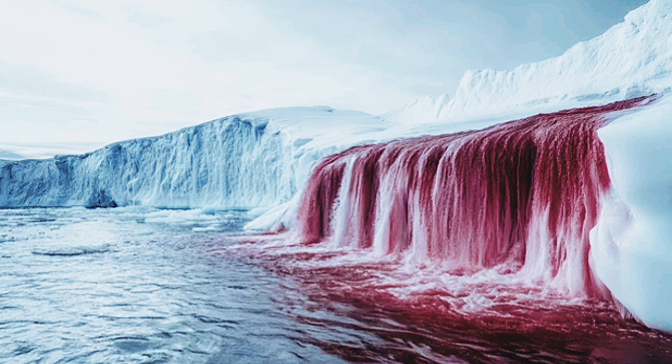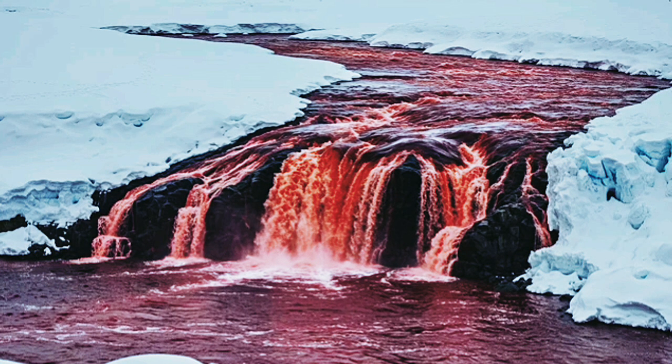Well, this is where it gets really interesting. They used XRD, which is sort of the standard for identifying crystalline minerals. Everyone expected to see strong signals for things like goethite. But the XRD results were underwhelming on that front. They found surprisingly little evidence for well-crystallized iron oxide or hydroxide phases. The expected signatures just weren't really there in abundance. Hold on. So the main suspect, crystalline iron oxide, wasn't actually the main component causing the color?